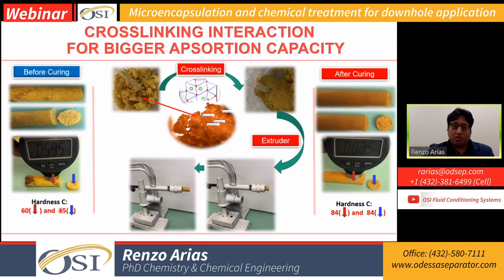Another important fact that I have to mention about this process is that before curing, the hardness is low, because after a specific period of time, the microencapsulation is going to develop a thick layer, and you can compare that. The hardness has increased from 60 to 80 for it to be uniform. And that's what you want, that thick protection at the moment of creating these materials. Now let's understand a little bit more of this chemistry.